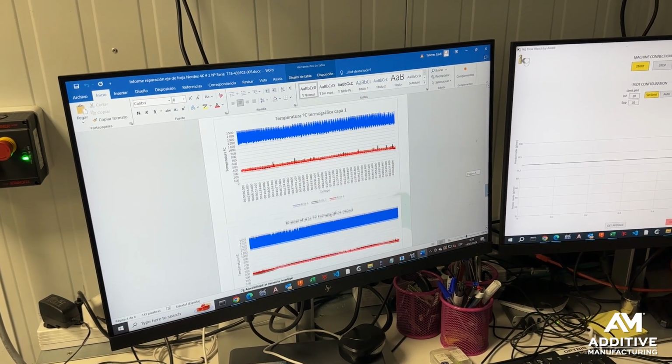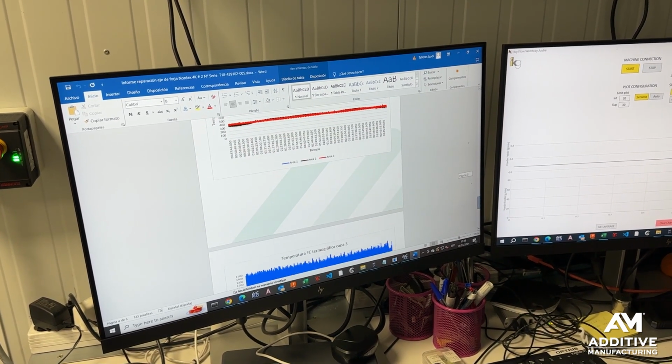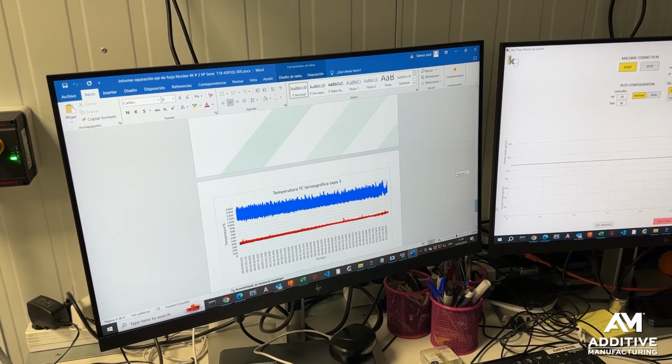Data capture, getting ready for a potential additional user that might have even greater traceability needs, like an aerospace industry application, for example. Something else the team recognized early on: the most effective DED in this application would come from controlling the heat-affected zone right at that juncture where the Inconel 625 meets the steel of the shaft. And to control that heat-affected zone, that meant heating the surface first prior to material deposition. So, how do you heat a shaft that big?